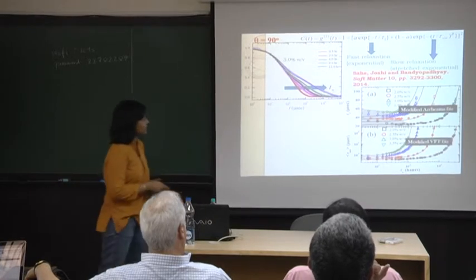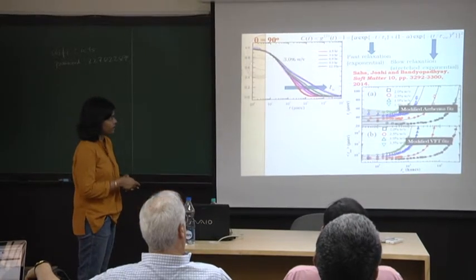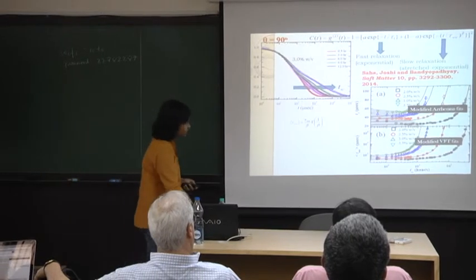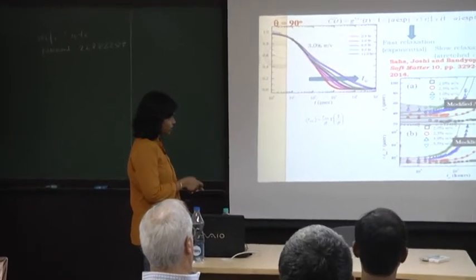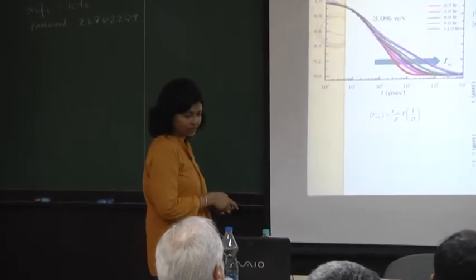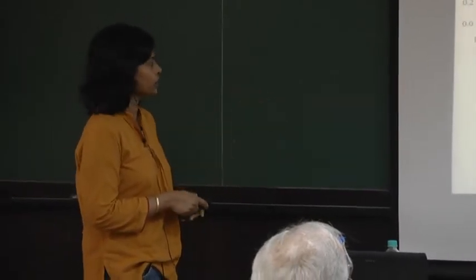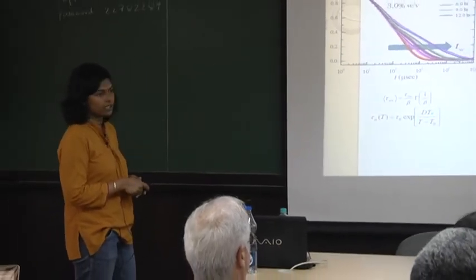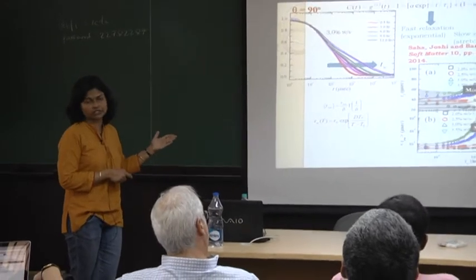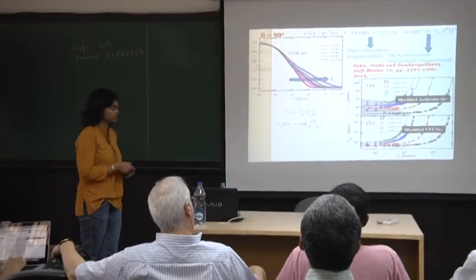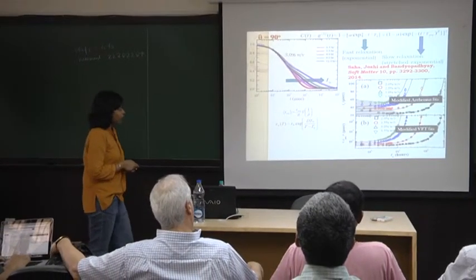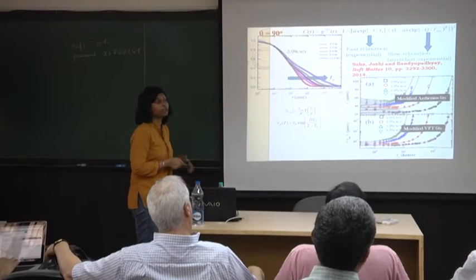I'd like you to have a look at these black lines going through them, which are fits to the data. So what have we done here? By the way, what we are plotting here is an average alpha relaxation time. I just showed you this form where the relaxation time for the slow relaxation process is the Vogel-Fulcher-Tammann form. T0 was the Vogel temperature, D is the fragility parameter, which tells you how fast you are approaching the glass transition temperature. All we've done to fit our time dependent data, yes.